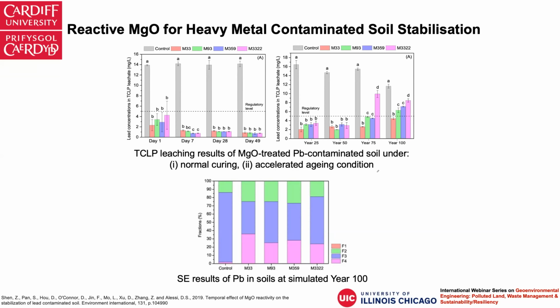So this data shows the high effectiveness of using reactive magnesia itself in remediating lead contaminated soils. After only 1 day, the leaching concentration is below the regulatory levels. In these figures, the number after the letter M means the reactivity value. The lower the value, the higher the reactivity. We can see that when we subject these treated soils to the durability test, which we designed to see how they perform over the years, the durability is quite different depending on the reactivity of the magnesia. This again raises the question of how we are going to use reactive magnesia to do the soil stabilization.